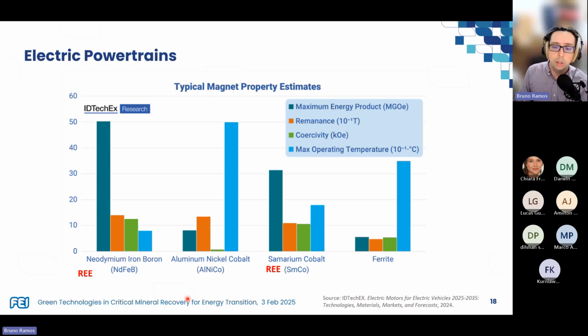And IDTechEx recently published an analysis on what can be done to replace these minerals. So the key point about these minerals is the magnetic properties, right? And if we look here, this is the typical material used in the powertrains, neodymium iron boron. It has a very high maximum energy product, remanence and coercivity, which relates to how long they remain magnetic after turning off the magnetization and the resistance to being remagnetized again. So the higher this number is, the better.